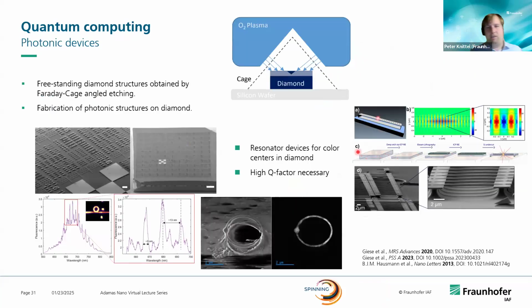How this looks in reality is you actually fabricate such photonic crystal resonators shown here, or for example ring resonators that contain NV centers, and the NV center, or the color center, then goes in resonance, and you make sure that all the photons that are emitted from your color centers are actually getting out of the resonator, and with that you can couple them. So there is a bit of a technological hurdle here, but this is in principle a bit easier than this dipole approach. So here also lots of our diamond films containing few NV centers are used, and also the films that contain lower amounts of 13C to get even higher coherence times.